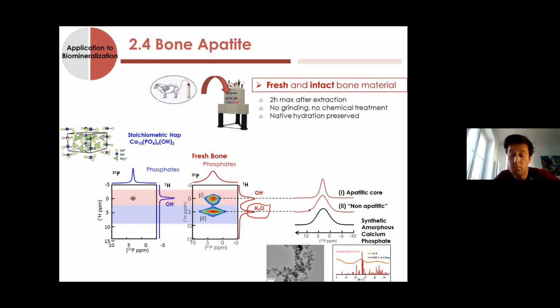So you have some examples - most of the examples corresponding to a gradient of disorder at the surface of the particles. You have beautiful examples coming from the group of Lyndon Emsley, now in Lausanne. He's studying nanoparticles of oxides with NMR, with this kind of technique, and he does see some. He starts by looking at the surface, then he starts to probe the subsurface by increasing the mixing time, so he's increasing the depth. And then the broadening of the signal decreases until it reaches the signal corresponding to the crystalline unit. So that's really an indication of a gradient.